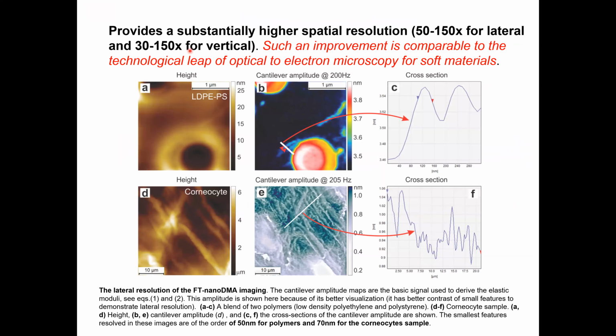Resolution. As I said, we already have a pretty good improvement in resolution. Technically, if we do theoretical analysis, we should be able to get down to as small as 10 nanometers for polymers. And here we see either 50 nanometers for polymers and 70 for corneocytes. We actually couldn't find finer structure on polymers or biological surfaces. So this is what we found, and we clearly see that we do resolve these mechanical properties on corneocytes and low-density polyethylene.